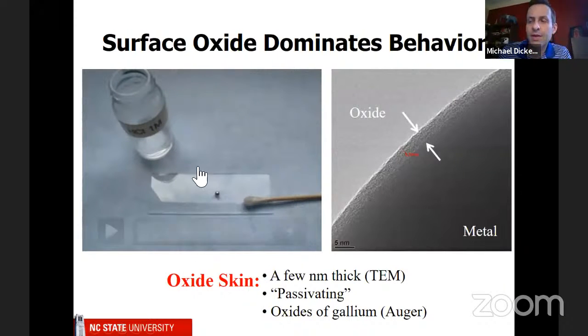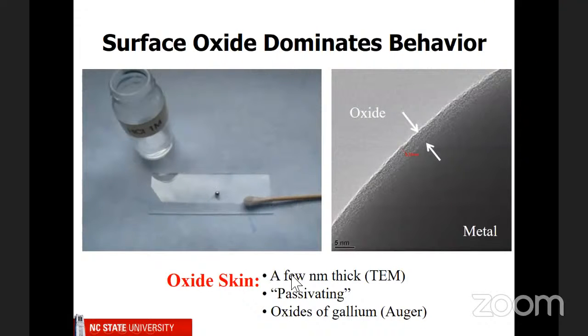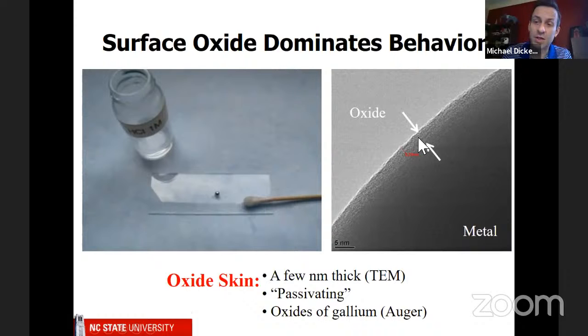So what do we know about this oxide layer? Well, it's a few nanometers thick. And one way we know that is simply looking at it. This is a transmission electron micrograph, TEM, which shows the thickness to be a few nanometers. And it forms spontaneously in air onto the liquid metal. Now, the second thing is it's passivating, and that's important because that means it forms, but it does not get thicker. This is the reason aluminum does the same thing, and that's the reason you don't find rust on aluminum foil. It just forms a thin layer and it stops.